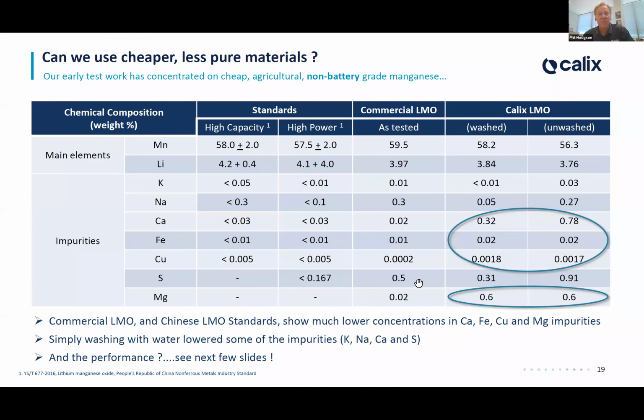We tested some commercial grade LMO, and when I go through the test results further down, you can see that in most cases they're conforming to these types of standards. Well, here's us. We've got pretty dirty LMO. Well, let's be honest. We've got high calcium, high iron, high copper, and high magnesium compared to the standards. Well, actually very high compared to the standards.